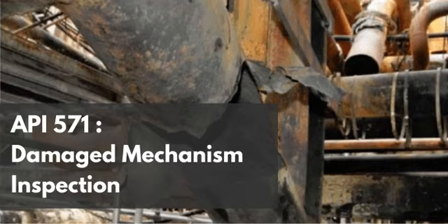So to prevent hot cracking, welding engineers do something very specific. What do they do? The weld filler metals, the consumables you use to make the weld, are chemically engineered so that the resulting weld deposit is not purely austenitic. It is actively engineered to contain a small, highly controlled amount of the ferrite phase. And API 571 gives us the exact number for this, right? Yes, it does. The text specifies that to prevent hot cracking during welding, these 300 series welds normally contain up to about 10% ferrite phase. Up to 10% ferrite. Right.